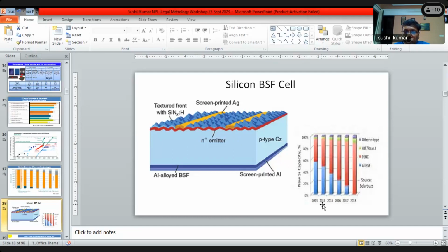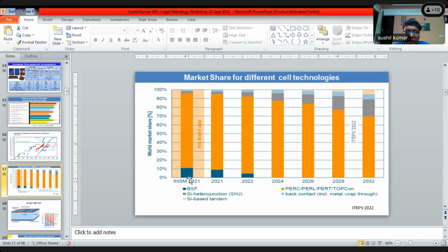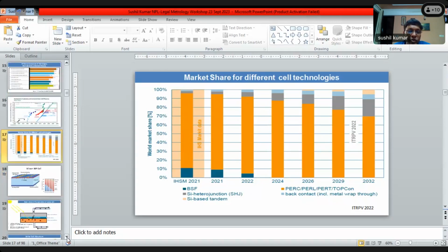So here data is shown from aluminum BSF, if you see this blue line, and it is changing with the red line with time. This is because of the change in the technology. So continuing with that, from 2021 to 22 and 23 it is all now different technology. Now it's a PERC solar cell and it is expected that different technology like TOPCon or the heterojunction solar cell will come. It's always evolving, and in the measurement one has to take care of these things also, that I'll show you.